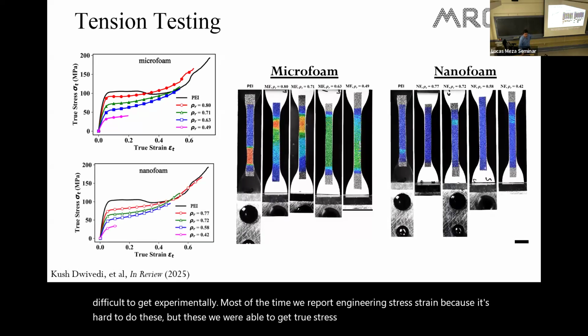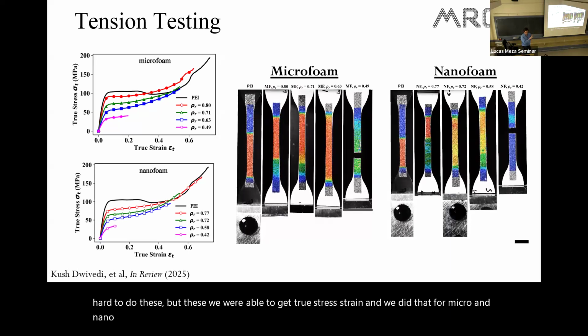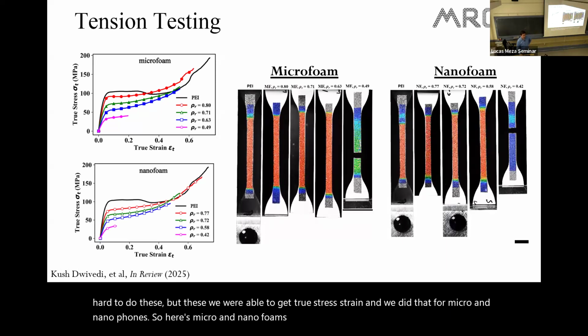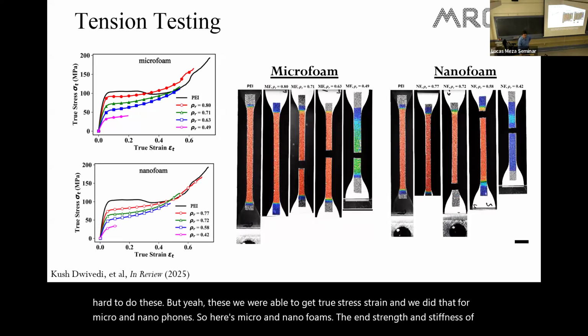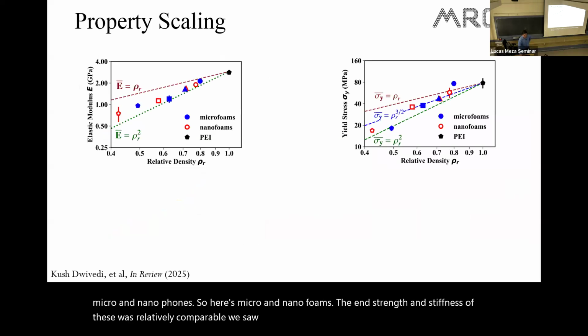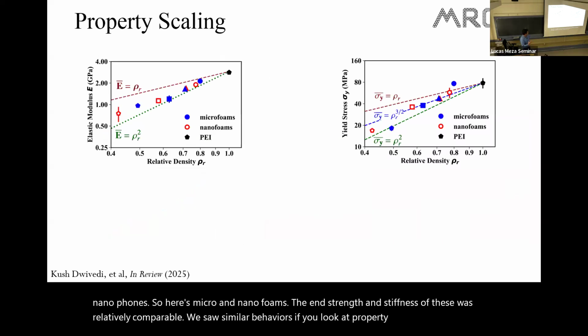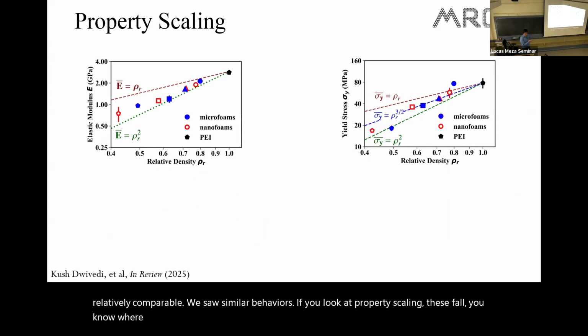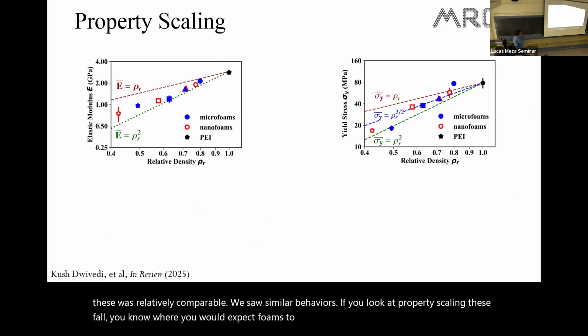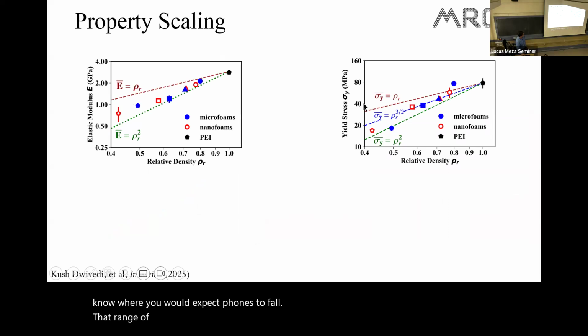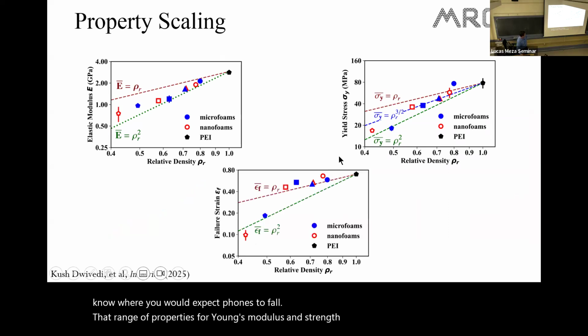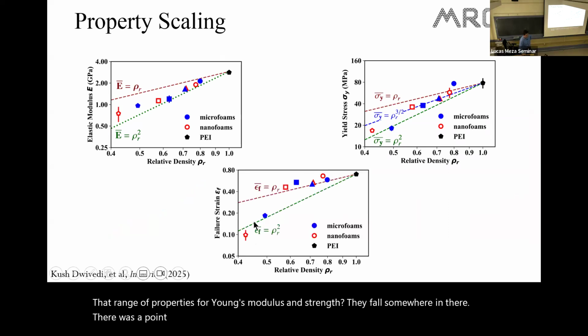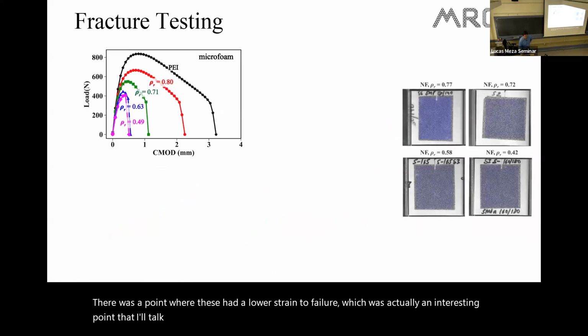And we did that for micro and nanofoams. So here are micro and nanofoams. The end strength and stiffness of these was relatively comparable. We saw similar behaviors. If you look at property scaling, these fall where you would expect foams to fall. You have that range of properties for Young's modulus and strength. They fall somewhere in there. There was a point where these had a lower strain to failure, which was actually an interesting point that I'll talk about in a sec if I don't run out of time.